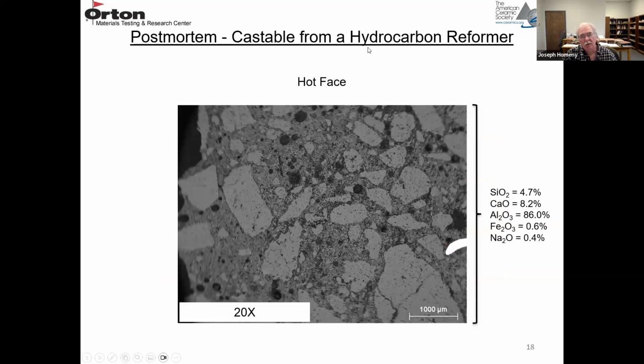So this is a castable. It's from a hydrocarbon reformer, and this is the hot face. So there's some silica, alumina, and lime. So this is a high alumina conventional castable. There's quite a bit of lime, so there's quite a bit of calcium aluminate cement present. And so this is the hot face after use. This bright spot here is actually a metal fiber. So this material was reinforced with a metal fiber to improve its thermal shock resistance.